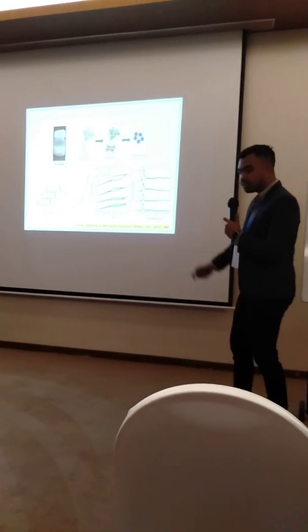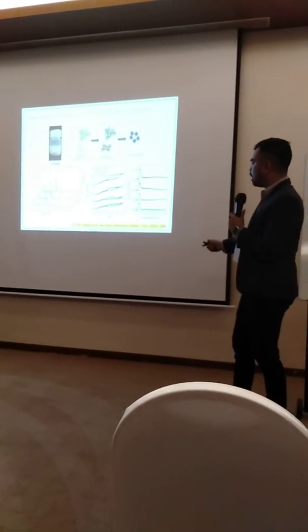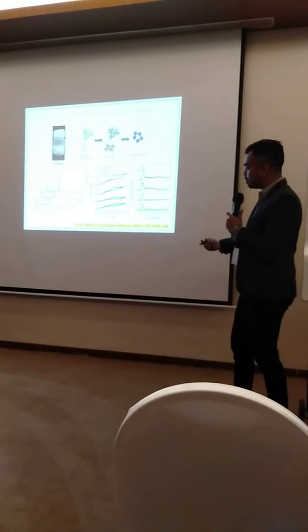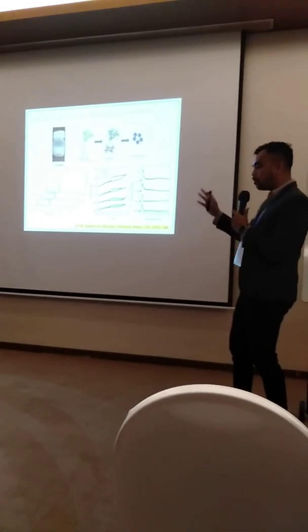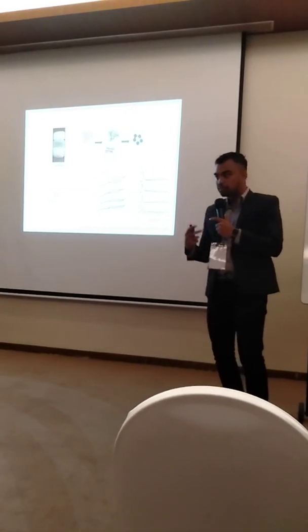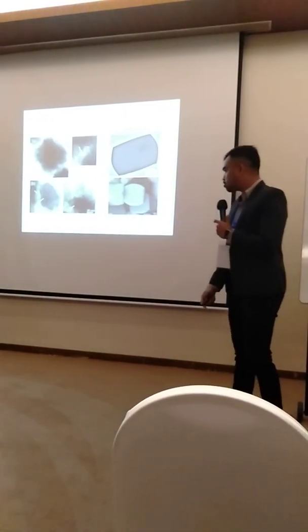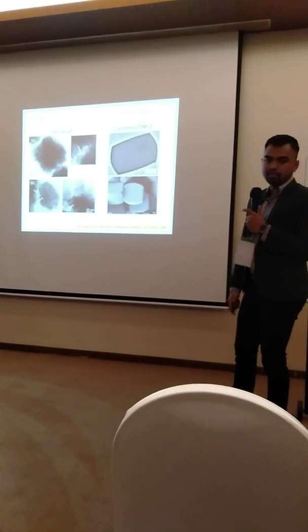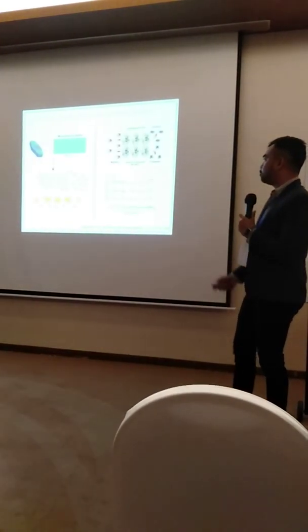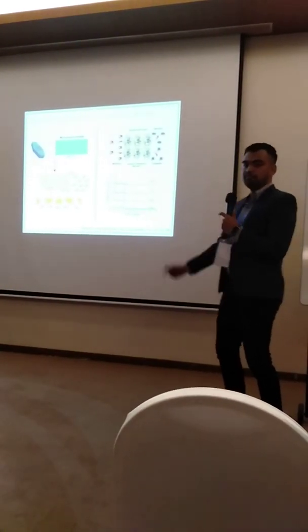You can see it is highly crystalline. You can see also the nitrogen adsorption-desorption isotherm. It has the H4 hysteresis, which indicates the occurrence of mesopores. And so this is the bottom-up strategy. We also have another strategy, which is the top-down.